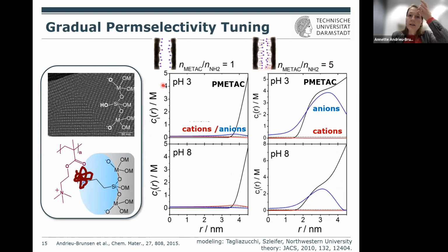To further understand the ion distribution along this pore size, and now keep in mind that this pore size is below 10 nanometers. We had a collaboration with the group of Igal Szleifer at Northwestern University, and they basically used their theory to first reproduce our cyclic voltammograms, but as well, and this is something that's just experimentally not possible, to get the ion distribution along the cross section of these pores.